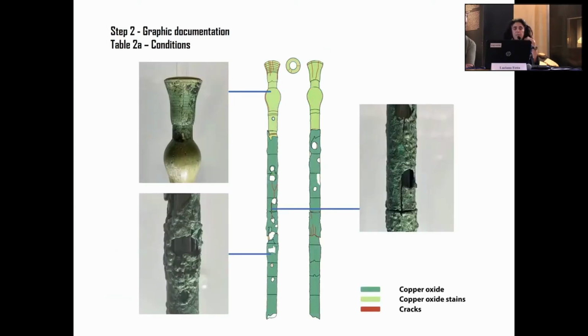The second table is about conditions, and this table involves a very, very close observation of the object. For example, in this case, it's possible to note that on the organic material there are very spread stains of metal oxides, of course coming from the metal parts, and that the copper alloy is very deeply oxidized. And also we note some cracks, and we register them on the table to identify and find them better.